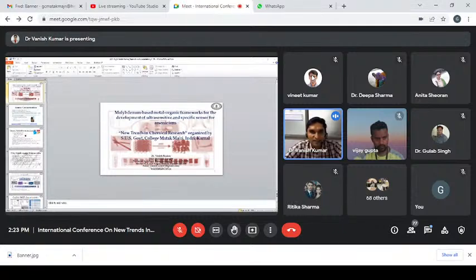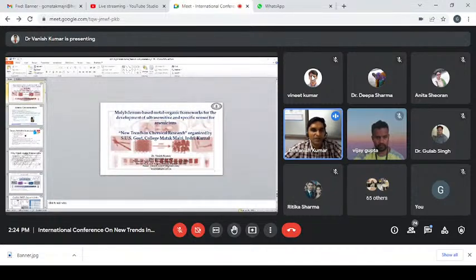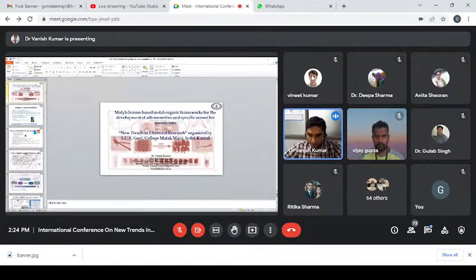So after that, we were not aware of what is the ratio of cobalt and molybdenum it is having. Then we conducted an elemental mapping of the product and found that there is 1:2 ratio of cobalt and molybdenum present in this MOF, and A is the same image of the same MOF, and B is the cobalt mapping, and C is molybdenum mapping. After analyzing this mapping, the software gave us 35% cobalt and 65% molybdenum in the structure in terms of combined metallic content of cobalt and molybdenum. After that we also confirmed this presence of 1:2 ratio with structural analysis.